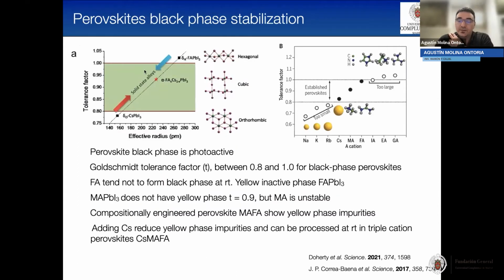Well, let's continue with the crystal structure of the perovskite. We have different phases, and the one that is active for photovoltaic applications is the perovskite black phase. This black phase, as I said, is quite stringent to the relative ion size. For example, if we use cations that are too small or too large, we move away from the 0.8 to 1.0 Goldschmidt tolerance factor, and so we move away from the black phase perovskite. In this case, for formamidinium lead iodide, it is very difficult to obtain the cubic structure because it is not stable; you can obtain it only at 150 degrees. On the other hand, methylammonium lead iodide does not have a yellow phase. The tolerance factor is 0.9, but this perovskite is not very stable because the methylammonium tends to leave the crystal structure.